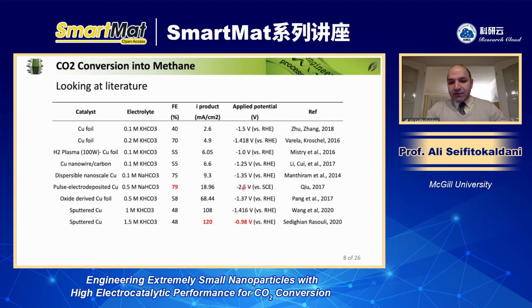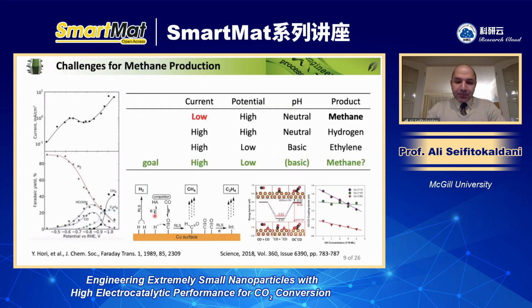And then it's also associated with very large applied potential, which means the system is not active. And if you improve the reaction rate by almost 1 order of magnitude, then the selectivity decreases. Although in this work, they achieve a very impressive low applied potential too. But if you notice, all of these works, people are working in neutral electrolyte. And in the next slide, I'm going to explain why people just work in neutral electrolyte, not alkaline electrolyte, even though they are using the flow cell system.